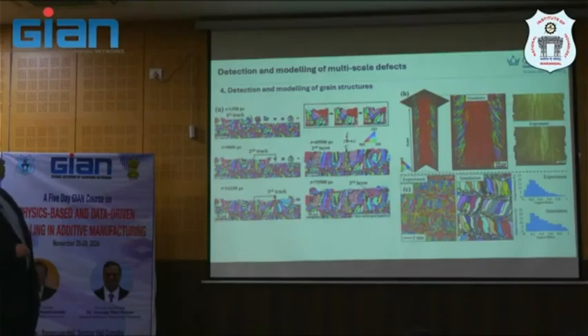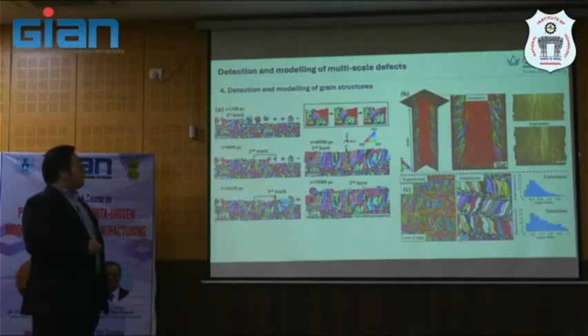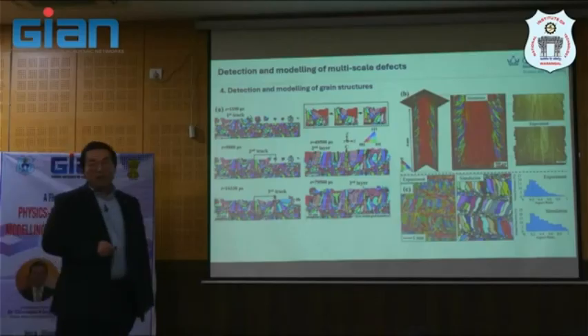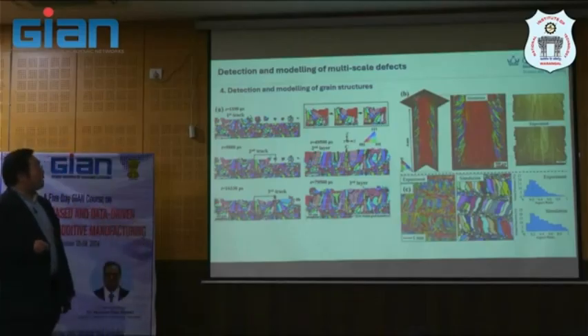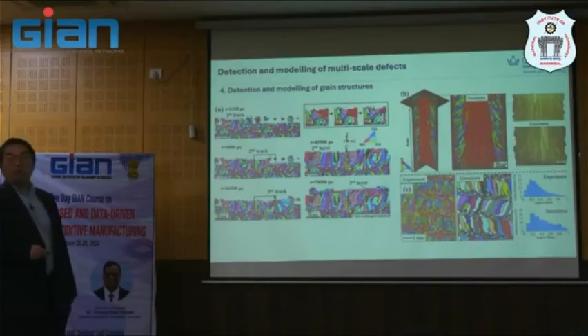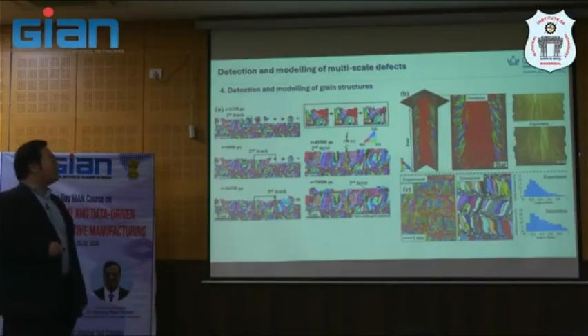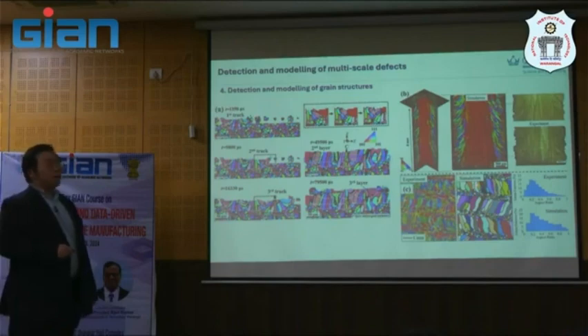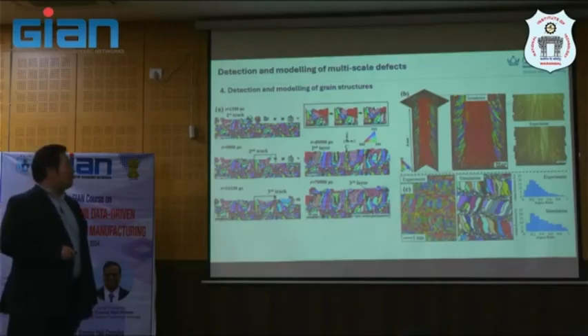But at the same time, if I'm not mistaken, this is from another group in Germany. You will see more directional growth here. Even though this is not single crystal yet, this may be from electron beam melting, and you will see the experiment and the simulation are in good agreement. Or the very traditional